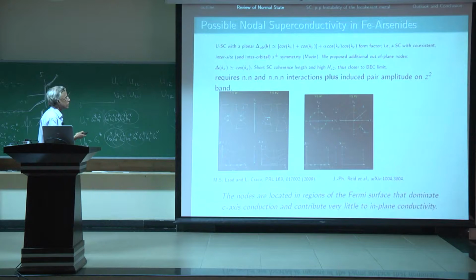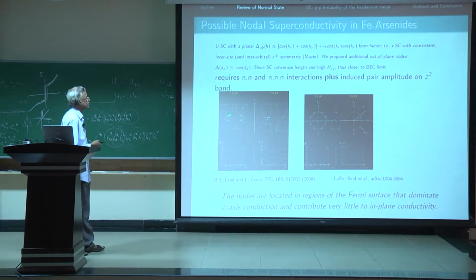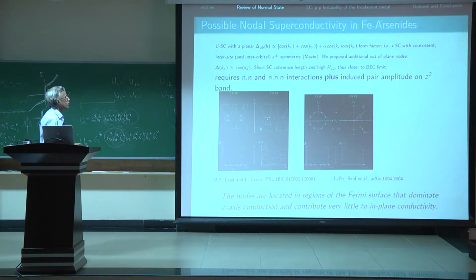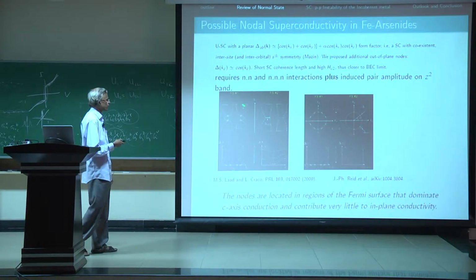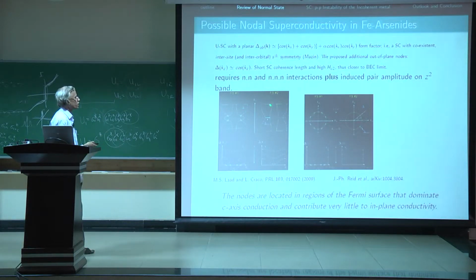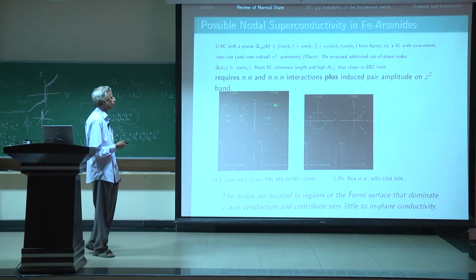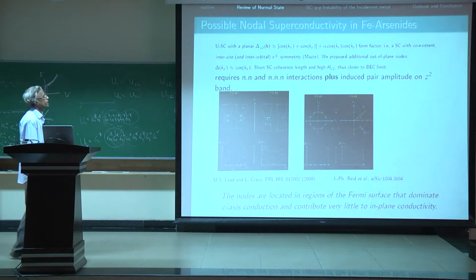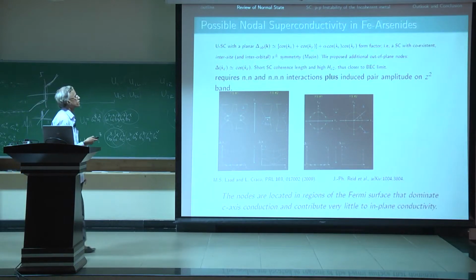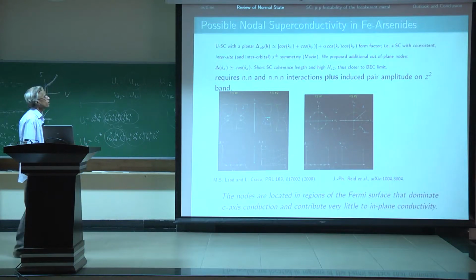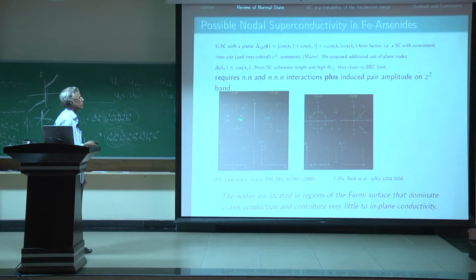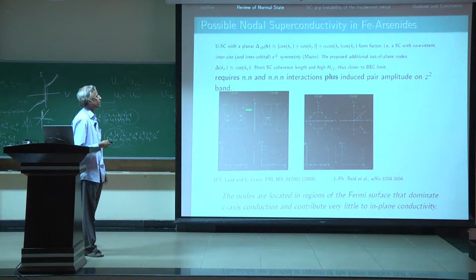Right, so this is basically putting it more explicitly in a figurative sense. If your Fermi surface, the central pocket, has a large degree of warping, then your gap function may intersect it at certain Kz points along the Kz direction, resulting in accidental nodes. But if there is very little warping, you will have no nodes whatsoever. So the idea in the early days of iron arsenide superconductivity was basically that the in-plane gap function has what is called extended S plus minus symmetry. And what we proposed is that depending on the degree of warping of the C-axis Fermi surface, this component which is out of plane could also kick in and give rise to additional accidental nodes in the gap.